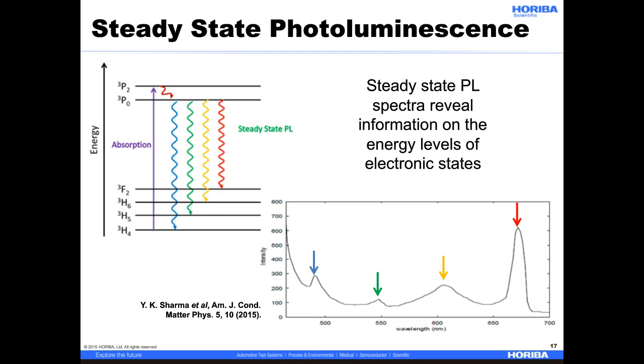In steady-state PL measurements, a CW light source is generally used with the mechanism for distinguishing the emission spectrum, whether that be with filters or a spectrometer. The detector response time in this case does not need to be fast since we are only interested in the spectral information in this type of experiment. The resulting spectrum can reveal information on the energy levels of the electronic states in the system. Borrowing from the rare earth example I showed earlier, we see that the various peaks in the PL spectra correspond to 4 different electronic transitions in the energy diagram.